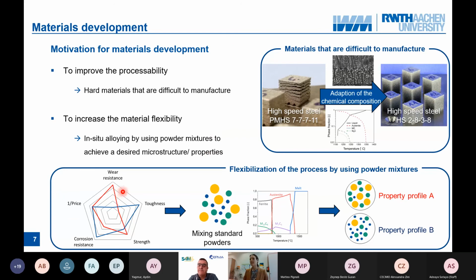For that, you first need to define your property profiles. Here we see two property profiles, one in red and one in blue. And then we take standard powders and mix them in different compositions, accompanied by thermodynamical simulations to see what happens at the solidification state. And then we get different materials with different property profiles with the same standard powders, only by mixing them in different compositions.